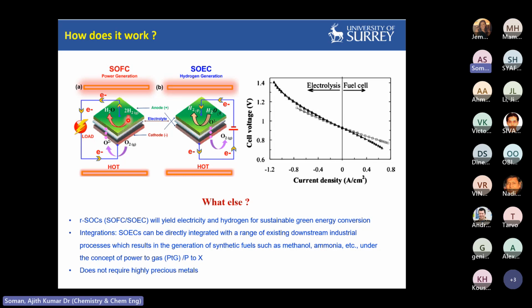This is how the SOFC is working. And the mechanism of SOEC is just the opposite. So we are converting hydrogen into water. Here we are splitting the same water into hydrogen. That's why the cathode becomes the main component, where the hydrogen is getting produced from water. If you supply or allow the electrons back to the cathodic side, the water can split into hydrogen. So the oxide species can travel through the electrolyte and reach the anode. It gets oxidized into oxygen. So this is how the two species can effectively split into hydrogen and oxygen if you operate in the SOEC mode.